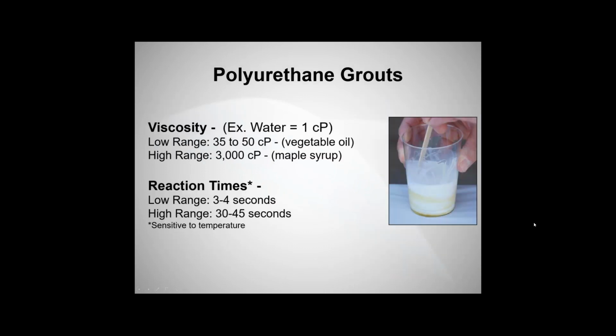So viscosities for the polyurethane grouts are low. They go from as low as 35 to 50 centipoise up to 3,000. Water is 1 centipoise, to give you a frame of reference. 35 to 50 is like vegetable oil, and 3,000 centipoise is like maple syrup. Reaction times for the urethane foams can be anywhere from a few seconds upwards to 30 to 45 seconds, to a minute, or 2 minutes or more, depending on how cool it is or how cool the material is.